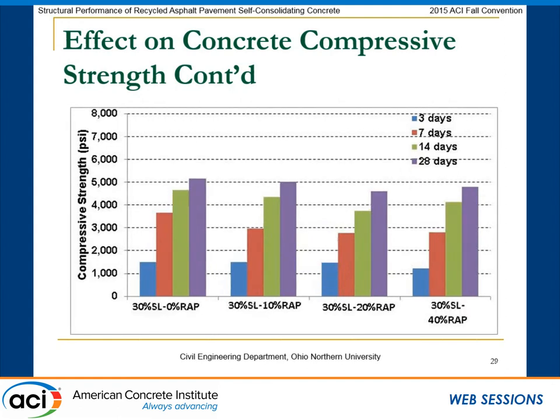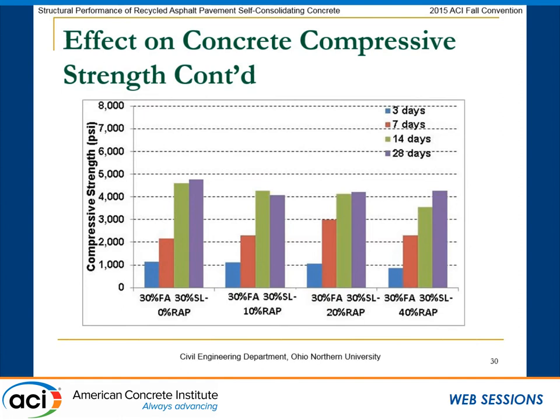But in general, when you add RAP, that would reduce your concrete compressive strength, and you can see this trend clearly here. 30% slag is closer to the control mix, which is 100% Portland cement. So it seems that slag improves the strength better than the fly ash. Okay, and you can see the trend here. Your compressive strength decreases as the RAP content increases. For 30% fly ash, 30% slag, maybe better than the fly ash, but it's not as good as the slag.